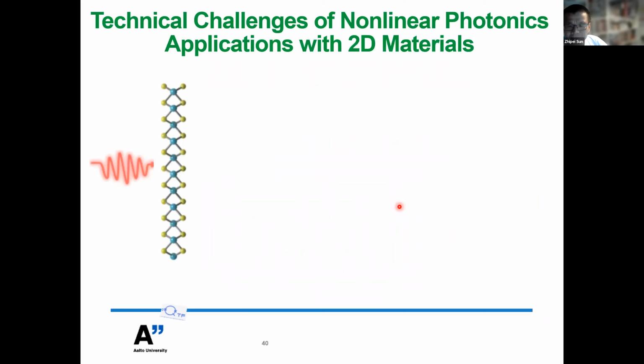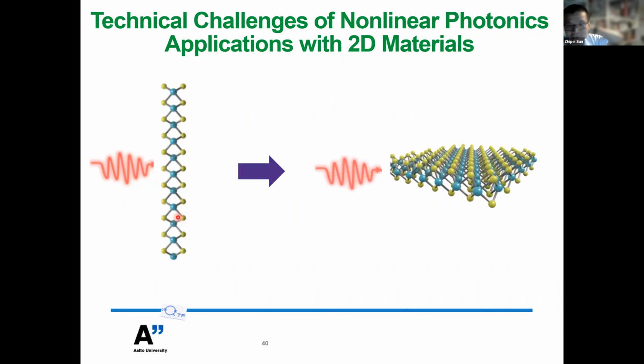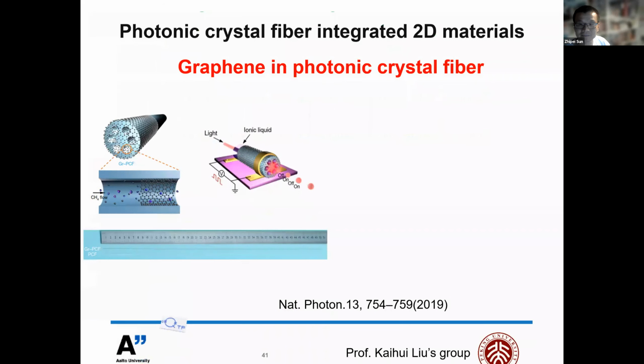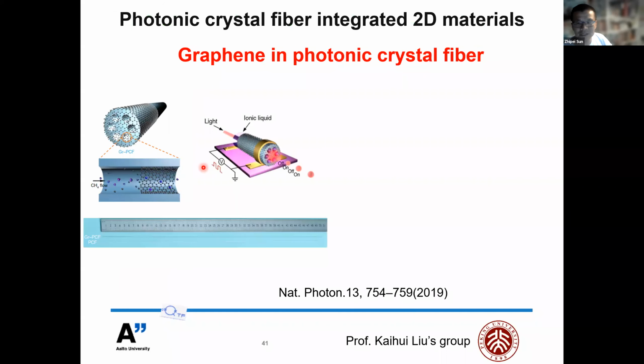As we discussed at the beginning, the absolute value of the light matter interaction strength inside of the 2D materials is very weak. This is mainly because of the very thin light matter interaction thickness. So you might think the easiest way to address that is to use the reverse mode interaction by integrating the 2D materials with different waveguides. This is what we tried: integrating the 2D materials with fibers to improve the light matter interaction.